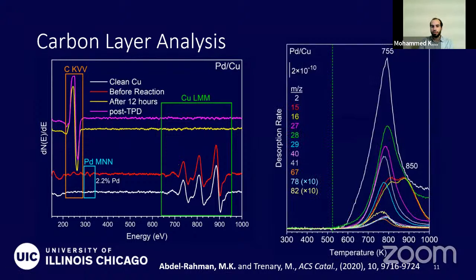And using temperature programmed desorption, where we monitor the mass spectrum as a function of temperature, we see we have major desorption peaks for the various hydrocarbons and their polymers. So we know we have a carbonaceous surface, and unfortunately, we can't identify what the nature of that surface is, other than it's some hydrocarbon-containing species.